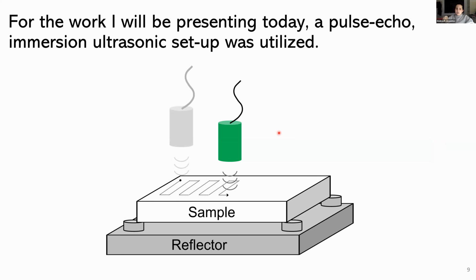The other thing is that we used a thickness independent method for the inspection. This was critical because we knew that there were small variations in the thickness of the parts that needed to be corrected for, in order to ensure that the mapping we were doing over space of these ultrasonic properties was actually representative of changes in the internal structure, and that we weren't just capturing thickness variations that are inherent with the manufacturing process. So essentially, we took the samples, raster scanned them, and obtained quantitative information at every single point. So a whole A-scan at every single point that we could then post-process to obtain quantitative information about the wave speed and attenuation for the two different sample sets that I will be discussing.